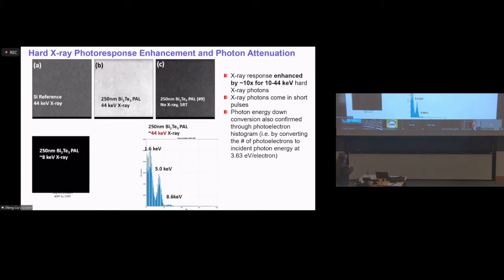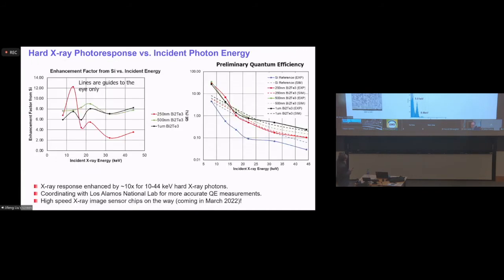You can see there's a strong reduction in the photon energy from 44 keV to somewhere below 10 keV, and it's mostly in the few keV regime. So that explains why you can absorb the photon more efficiently in silicon.